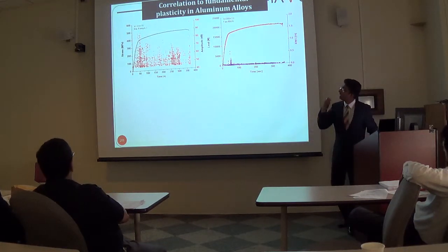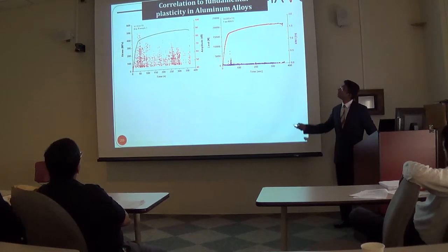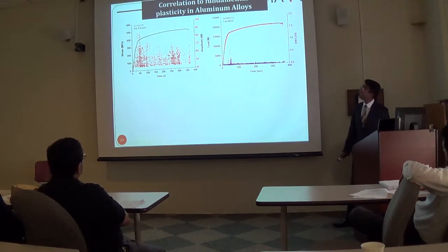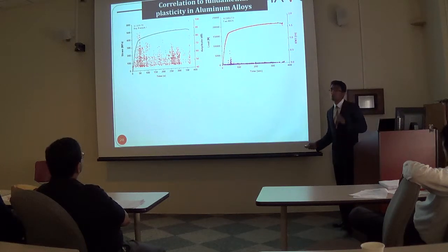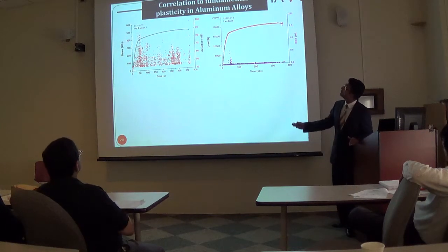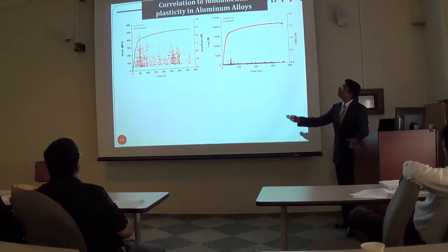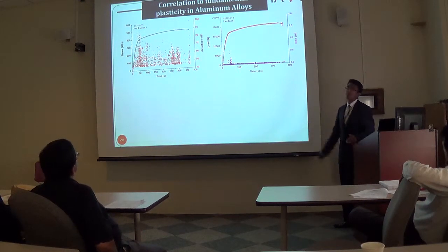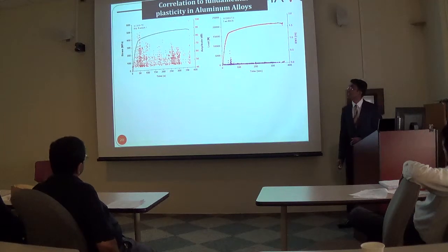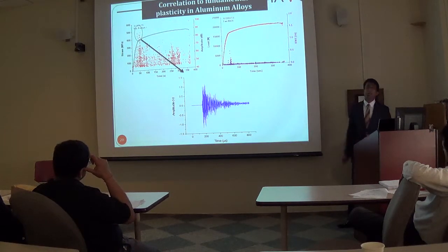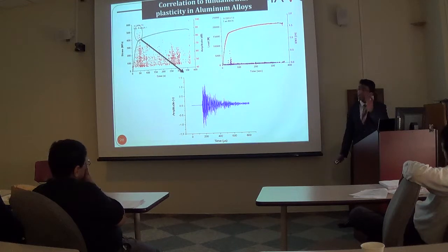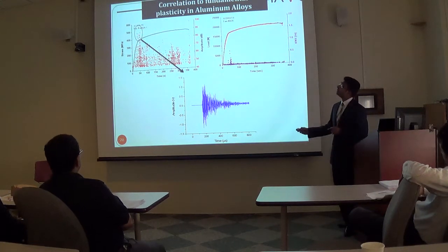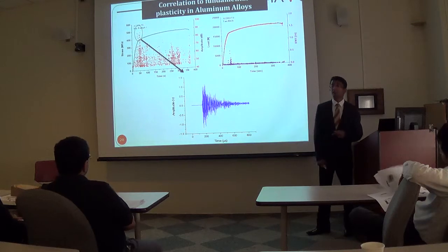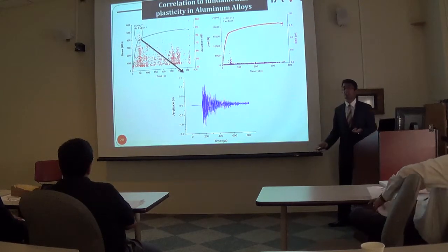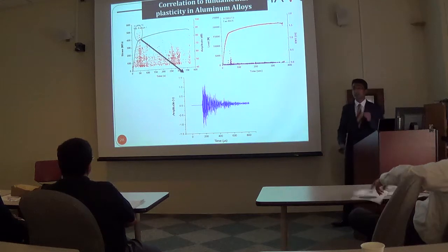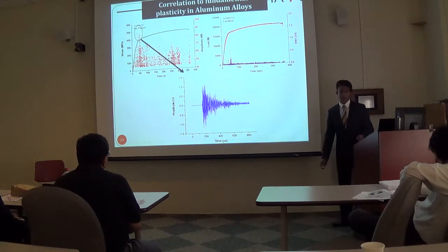So the mechanical testing of the aluminum alloys was carried out, and it was loaded intentionally until failure, as you see here. And what was seen in real time was that the AE features that were correlated to the applied loading condition were very interesting. Right at the point of yielding, you could see high amplitude AE signals being generated, as well as high RMS values. The signals that corresponded to the high amplitude signals right at the point of yielding had burst type emissions. These burst type emissions were not seen with the signals that were picked up prior to the yielding. And so again, similar to the AZ31 alloy, you can see how there's a shift in the actual wave signature upon the yielding of the material.